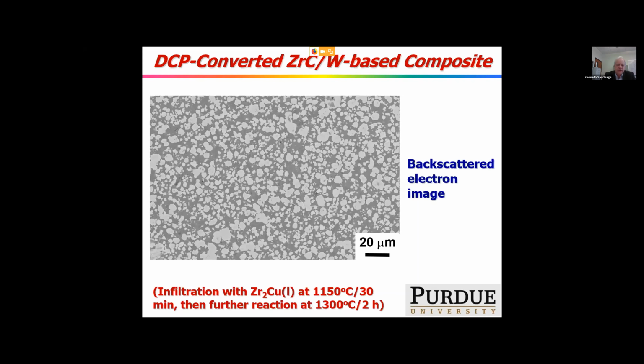If you zoom in, you can see the dense zirconium carbide bearing matrix and the brighter tungsten particles. A pretty homogeneous distribution of both phases. So we went from a 50% porous preform to a fully dense part, and again, the dimension changes are less than 1% typically.